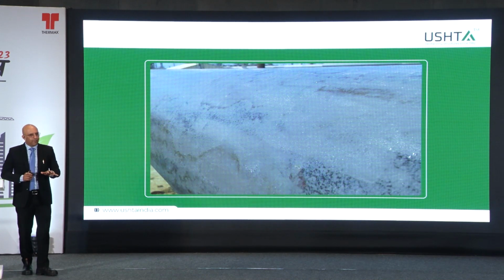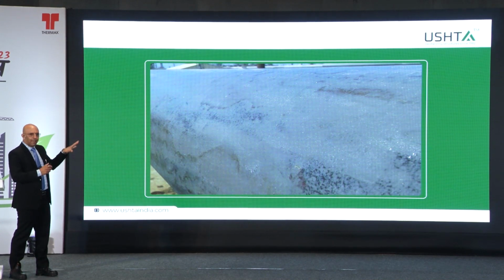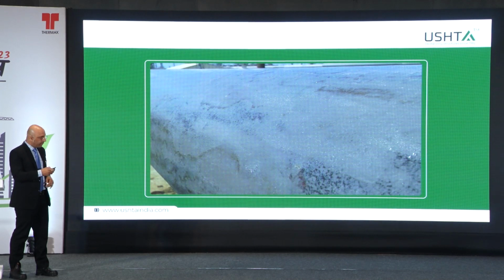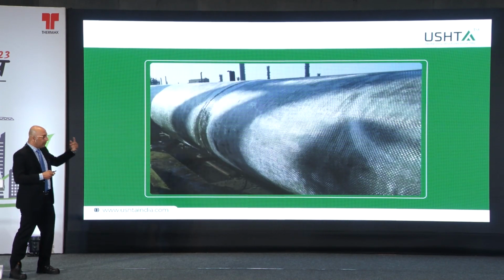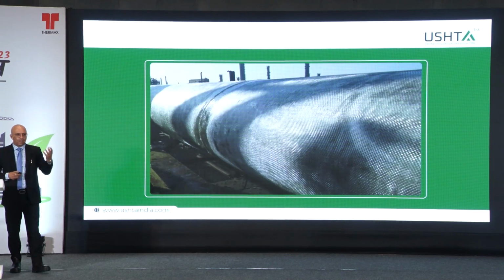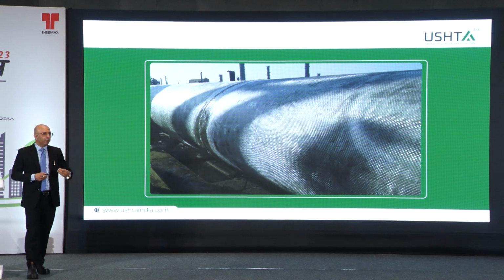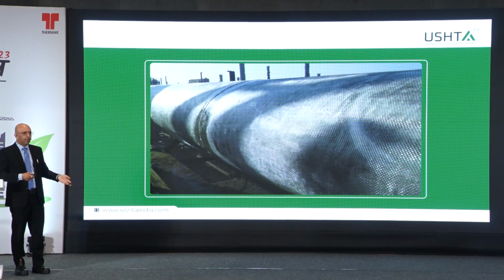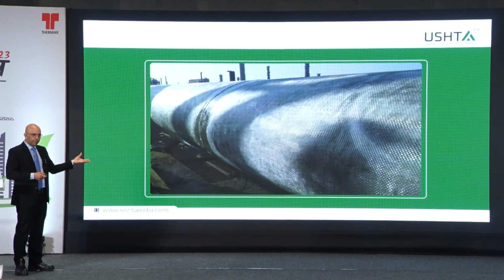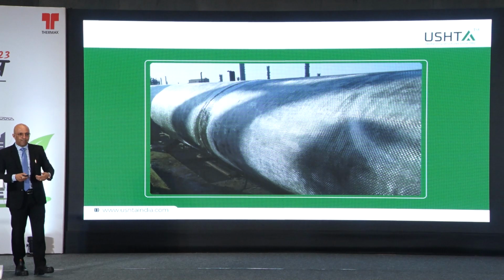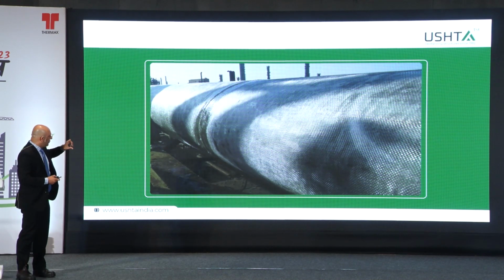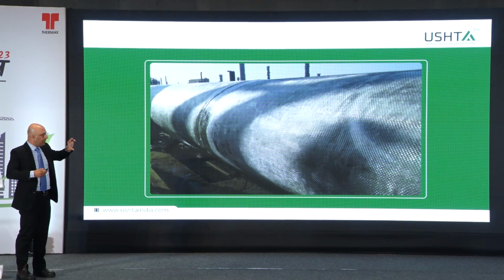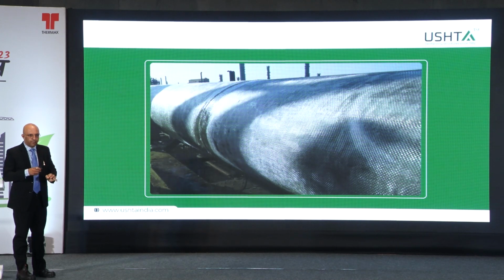So, we designed this in such a way that this can expand accordingly and will not crack. And later on, we applied one layer of glass because carbon is a conductive material, and normally you do not apply carbon directly to the steel surface because some of these lines are charged. So, to insulate, we applied glass fiber, and we had to pass through a holiday test. So when you do this first layer, they'll take a holiday test, they'll pass current through this, and if there is any void, even fine void, there'll be sparks. So we had to give 100% holiday free pipes.